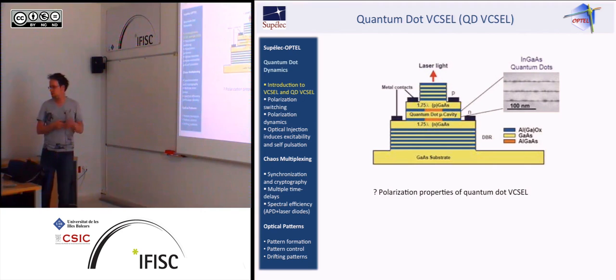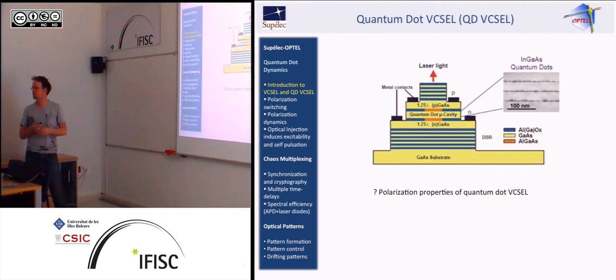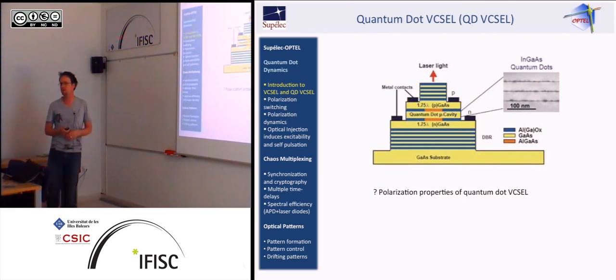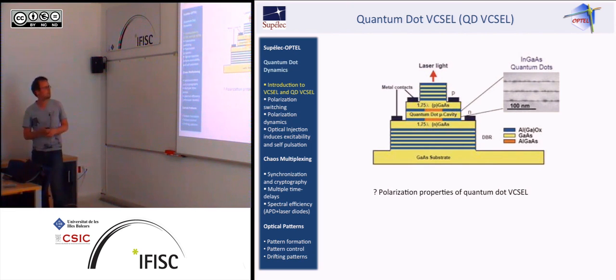This device is quite sophisticated. I mean, it's quite modern, or technologically advanced, in the sense that it has an oxide confinement here. There are aluminium gallium oxide layers that confine the field and make this circular oxide aperture of the device. And it also has an intra-cavity contact. So the current is not injected from the top, but directly into the active layer, which makes things much better because the current doesn't have to flow through the mirror before entering the cavity. So those devices have much better performances than others.